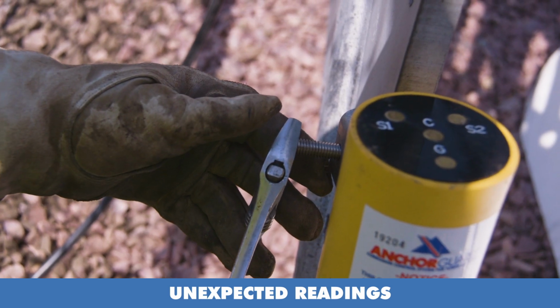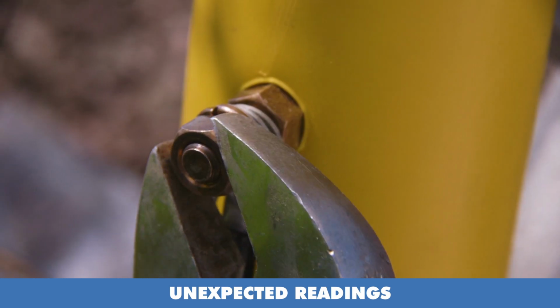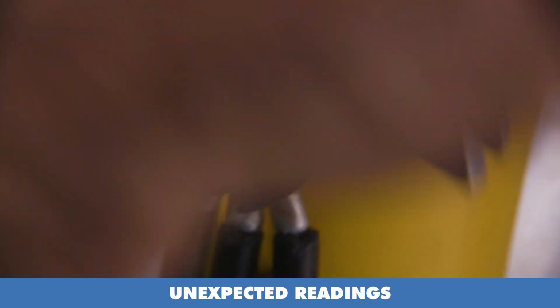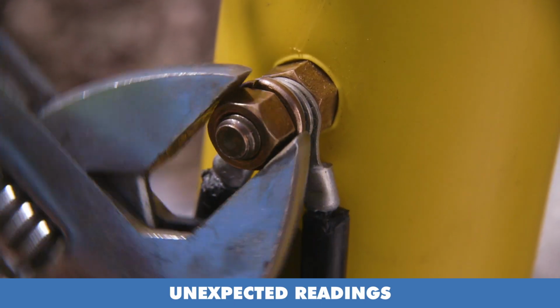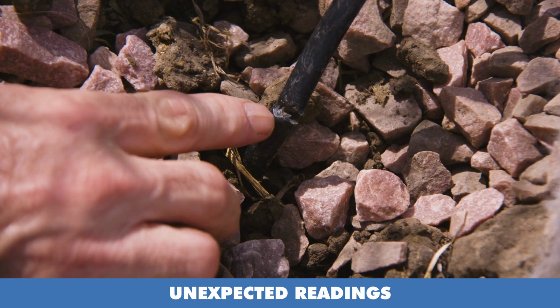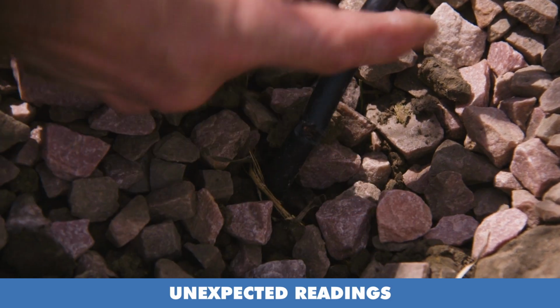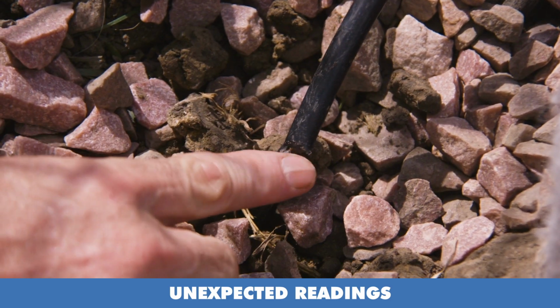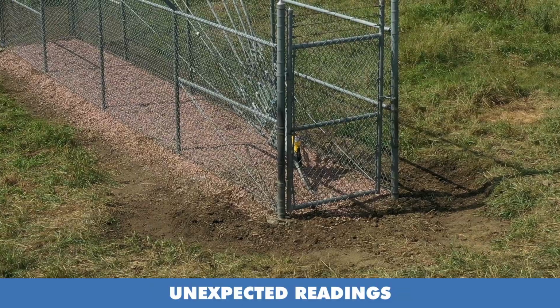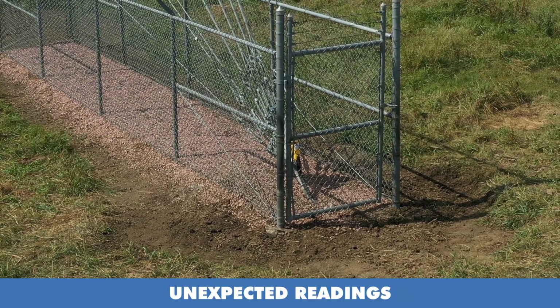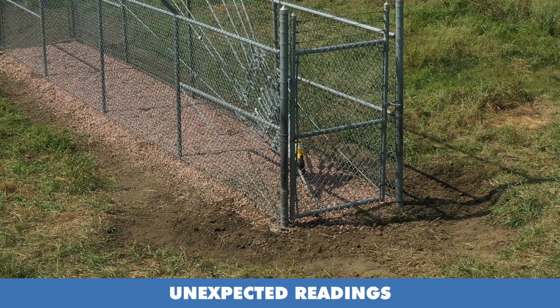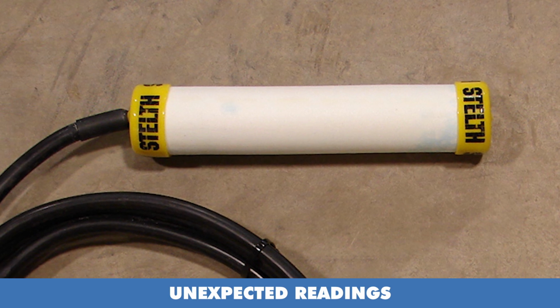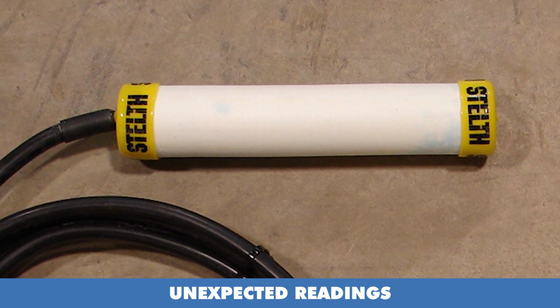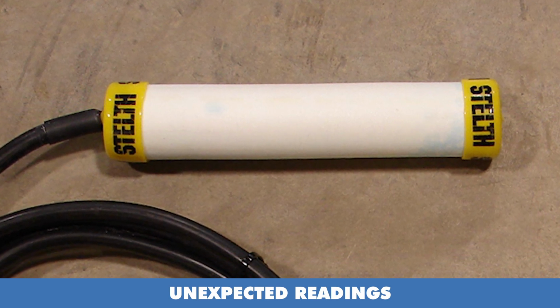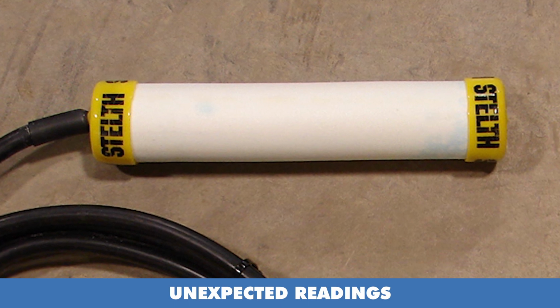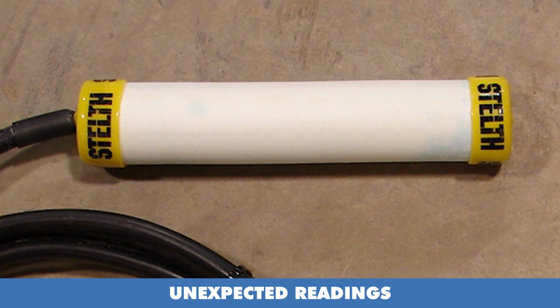The test head clamp or the anode connection lug are not secure. Make sure they are seated properly and tightened securely. The anode and/or test head leads have been cut. Inspect them fully. In the event that none of these is a problem, the test head could be defective and should be replaced. If readings are unusually low or do not behave close to what is expected, the buried portion of the test head may be damaged or defective, and the test head should be replaced.